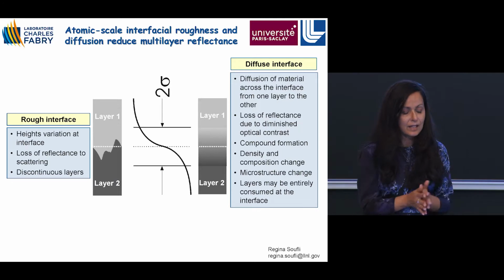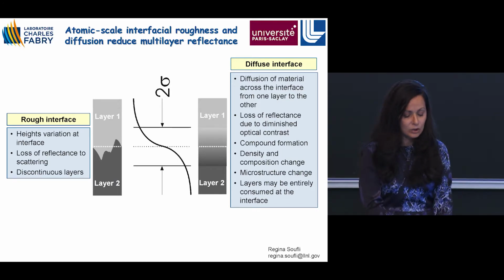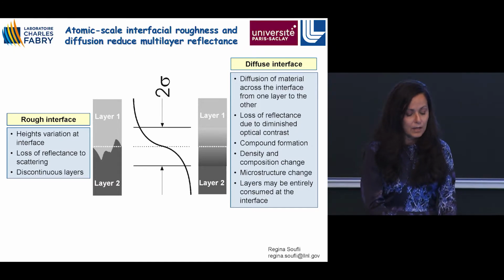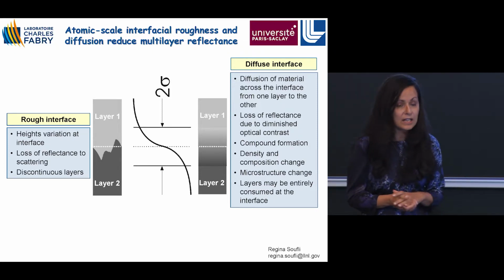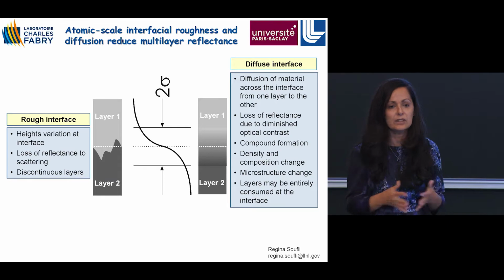We can roughly separate these interfacial effects into two categories, roughness and diffusion. In reality, both phenomena happen at the same time. By roughness at an interface, we mean the height variation at the interface, which leads to loss of reflectivity due to scattering.